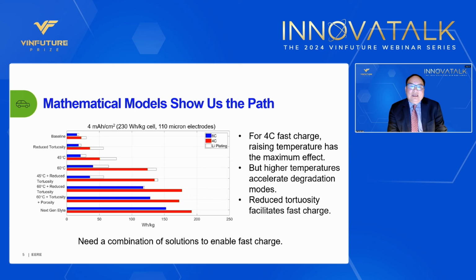So this plot shows you a lot of interesting things. The top of the table is a cell built at 4 milliamp hour per centimeter square, basically a typical loading for EV batteries. With this kind of loading, normally you will get 230 watt-hour per kilogram at C/3 rate. But look, if you fast charge them at the 6C rate or the 4C rate, and you watch the lithium plating, you can see on the top, the baseline is for 6C and 4C, and look at the bottom, it's only about 20 or 30 watt-hour per kilogram. See that? The next row you do is you model with reduced tortuosity. You can see you can get more specific energy.